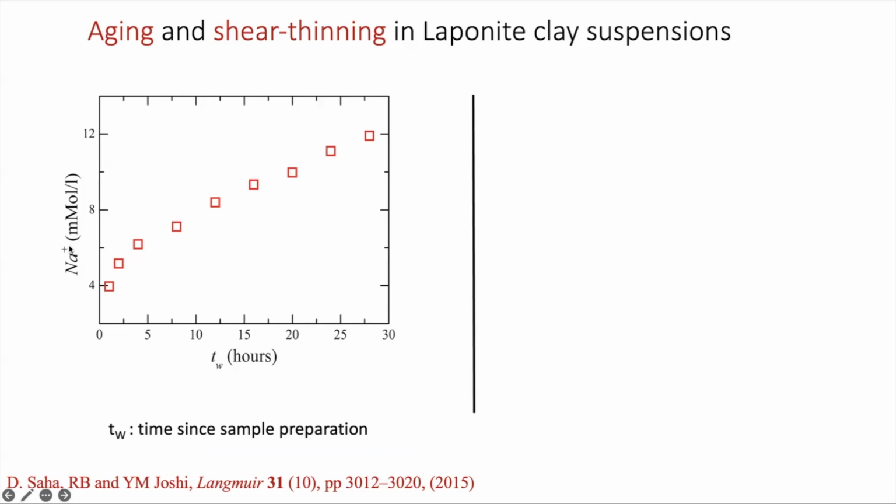What we've done here is we've measured the sodium ion content in the bulk water medium using a sodium ion sensor. You can also do this with conductivity, but for that you have to assume that DLVO works, which may not be entirely true. But if you just measure the sodium ion content in water with the age of the suspension, so you're not really disturbing it, you're just letting it evolve, and measuring the sodium ion content in millimolar per liter, sure enough, over here we have measured for 30 hours, and you can see that the sodium ions continue to build up.